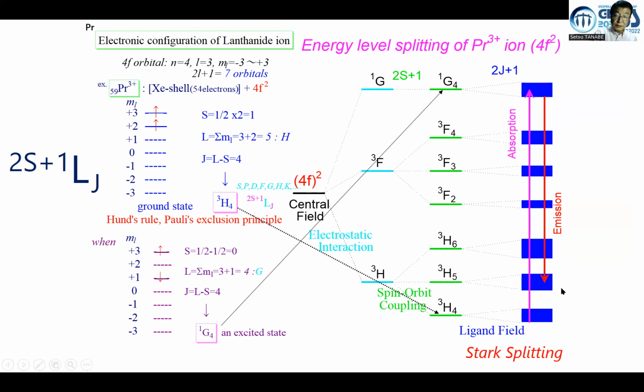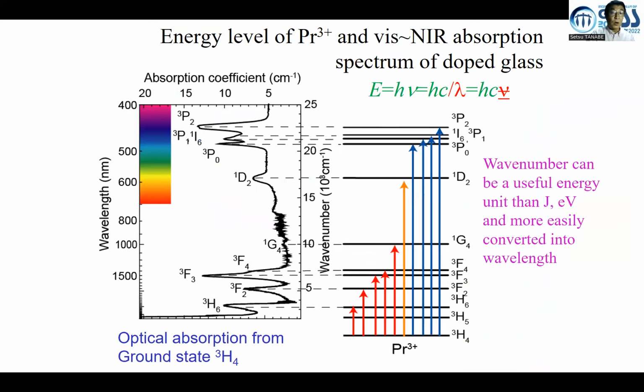So the spectral shape depends on how the Stark splitting happens, depending on the local structure of the host material. And this is the absorption spectrum of praseodymium-doped glass. And on the y-axis, I took the wave number instead of absorption coefficient or wavelength, the inverse wavelength is plotted here, and the absorption coefficient is on the x-axis. So we can see the corresponding energy levels, and the excited state can be estimated. Wave number can be a more useful energy unit than joule or electron volt, and is more easily converted into wavelength.